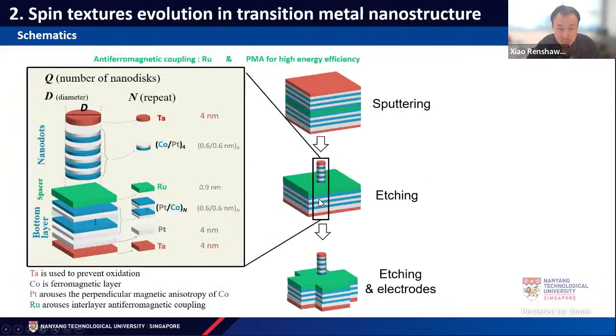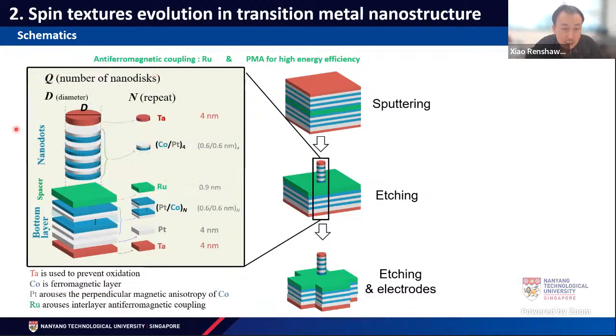Now I'm going to discuss some of our experimental results. In our study, as I said, we deal with localized skyrmion-based or skyrmion-like structures. We build multilayer structures. For the antiferromagnetic coupling, we use ruthenium, and we play with the thickness of the ruthenium to get the ideal antiferromagnetic coupling. For the perpendicular magnetic anisotropy, the out-of-plane magnetization, we use cobalt platinum multilayers, and we can play with the repetition of the layers. On the left side here, let me change to a pointer, this is our zoomed-in microscopic structure of the device.